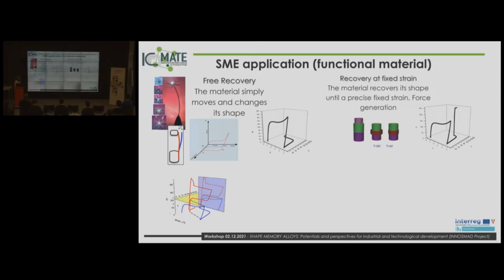The second kind of application is recovery against a fixed strain, and then we open the possibility to different junctions, connections, tube connections, rings to contain two parts of a device, of a tube, and so on. And the particular property of shape memory alloys is that when we deform, for example, the ring, and then we increase the temperature, the ring closes and tries to recover its initial shape, but against the fixed strain. And then the ring continues to apply force. This is not a static junction, it's an active junction.